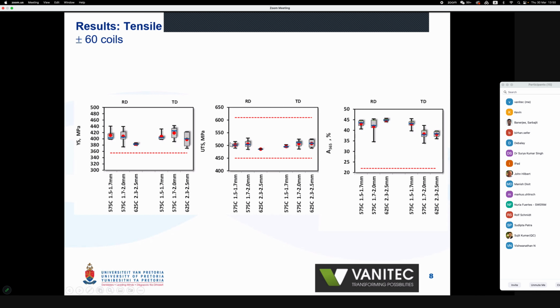As with many other steels, UTS is fairly constant across the board. And then as far as the A50 elongation is concerned, it is comfortably above the minimum spec, although the elongation was comfortably higher in the rolling direction.